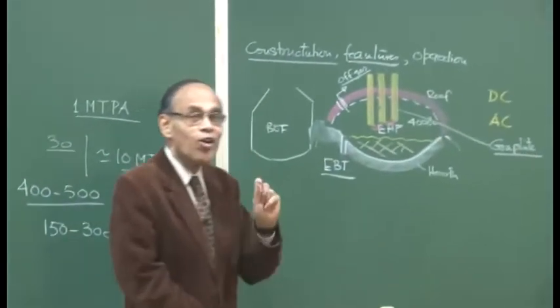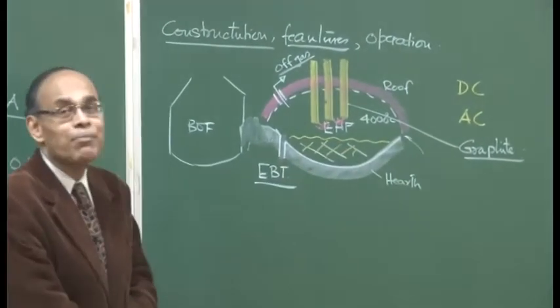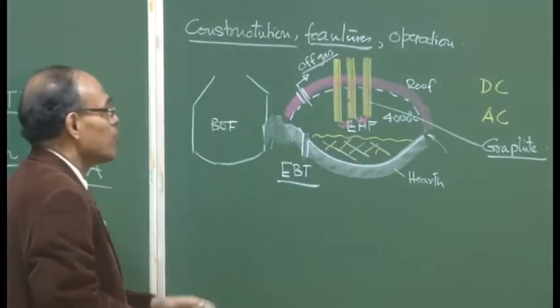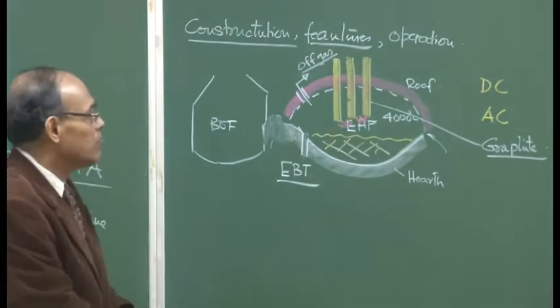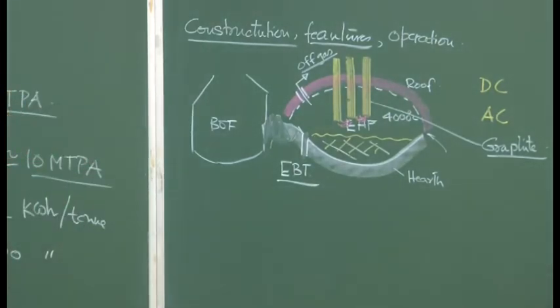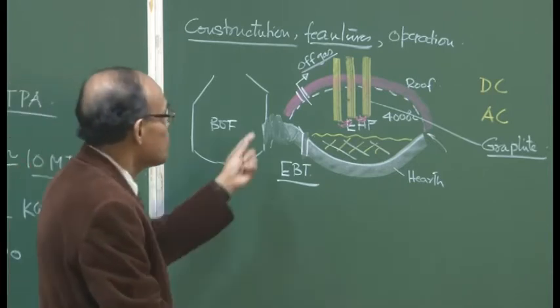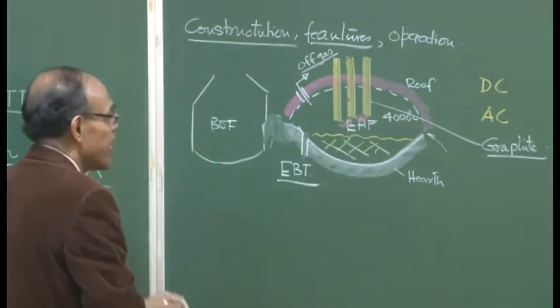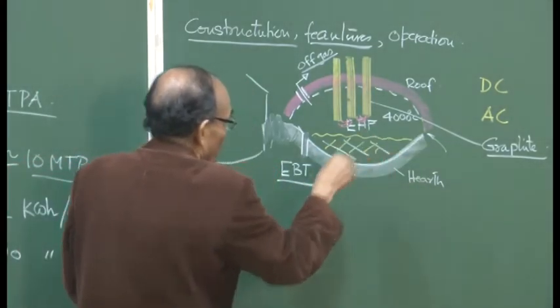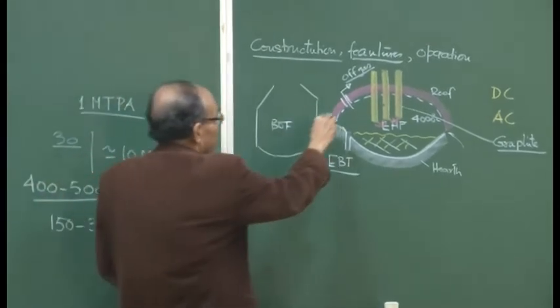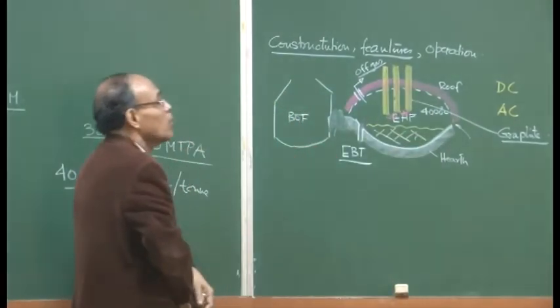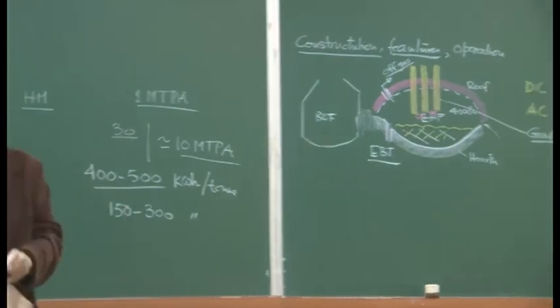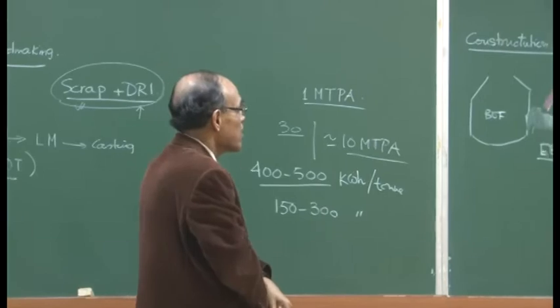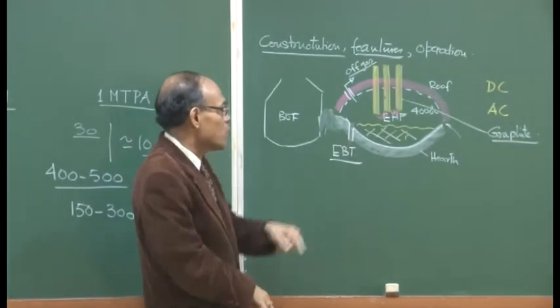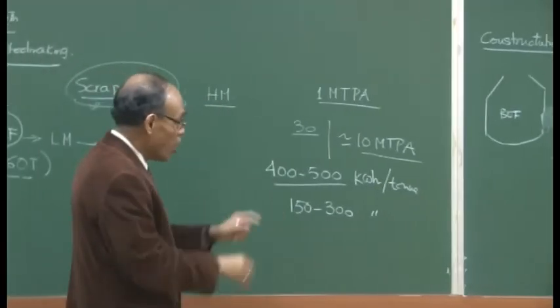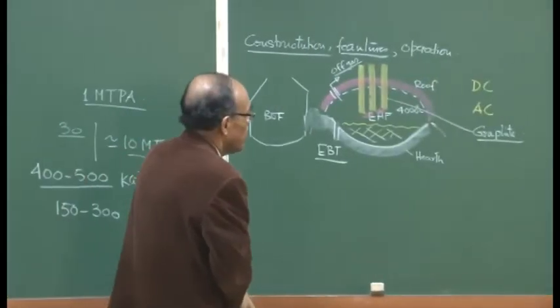So, in steel making industries, all arc furnaces are going to be lined with basic material, and the hearth is basically lined with magnesite. On the other hand, for the roof, different kinds of material are going to be used, mostly chromites as well as magnesites. They have their different requirements, as I have indicated. The hearth region is possibly more important for corrosive action of the metal. On the other hand, the thermal resistance or the heat resistance of the roof is going to be far more critical, and that tells us the reason why different kinds of refractory materials are used in different parts of the furnace, roof as well as the hearth.